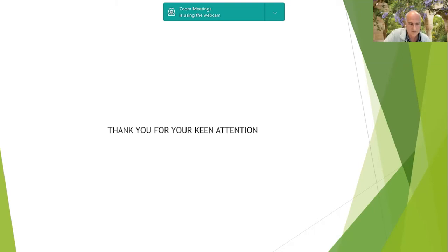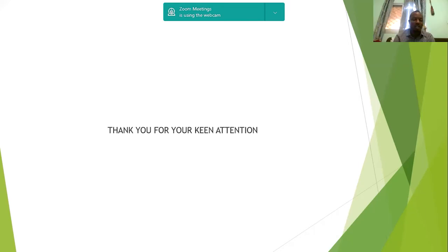Thank you very much for that suggestion. Could I just follow up for 1 minute? Go ahead. Okay, thank you, Professor Chinje. Exactly. We have established contacts with these cement companies, particularly Cementcam. We contacted them. We didn't have a successful meeting last week, but we got feedback from the responsible personnel that they were very interested. However, the point is also true: the clinker is imported, but we are focusing on how profitable this is. Even if the clinker is imported, you are reducing your clinker from maybe 70% if you're using pozzolana to 50%. That 20% margin is huge profit, even if the clinker is imported.